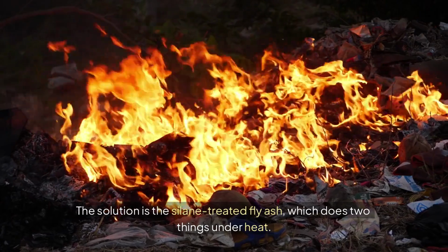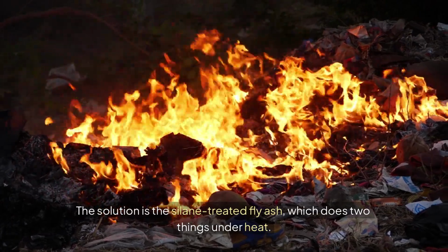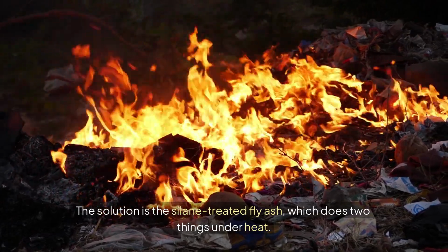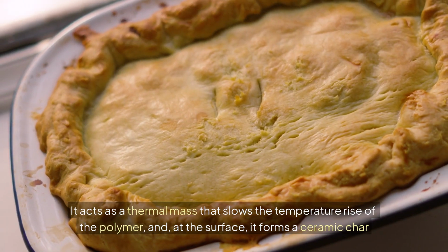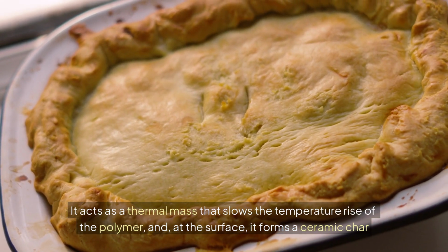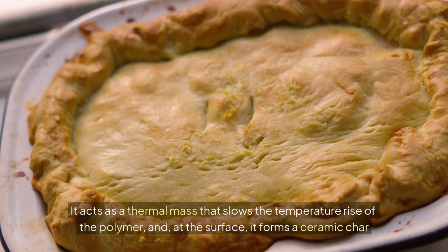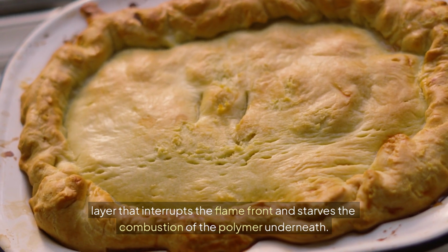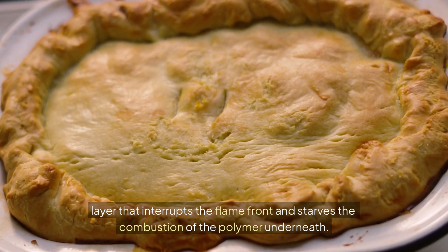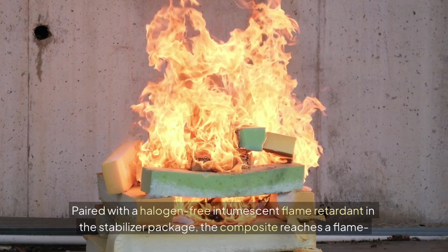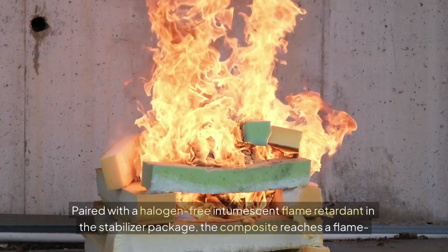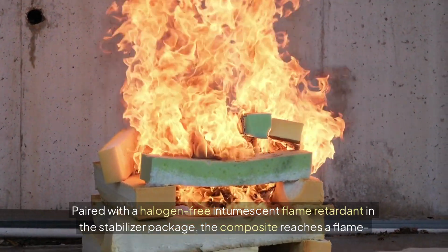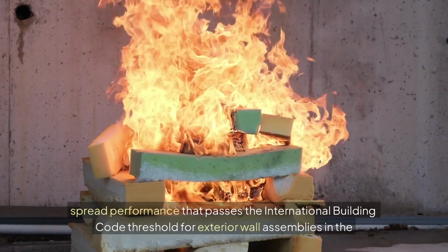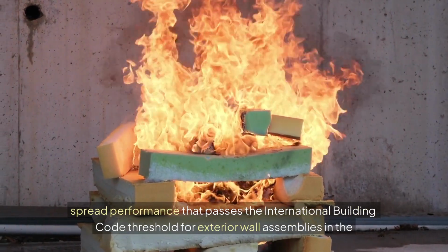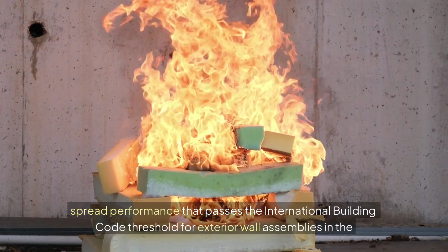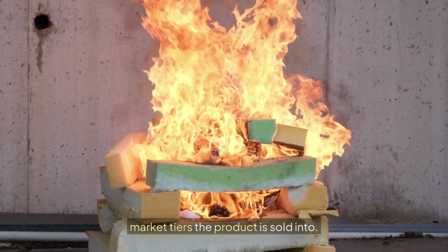The solution is the silane-treated fly ash, which does 2 things under heat. It acts as a thermal mass that slows the temperature rise of the polymer, and at the surface, it forms a ceramic char layer that interrupts the flame front and starves the combustion of the polymer underneath. Paired with a halogen-free intumescent flame retardant in the stabilizer package, the composite reaches a flame spread performance that passes the International Building Code threshold for exterior wall assemblies in the market tiers the product is sold into.